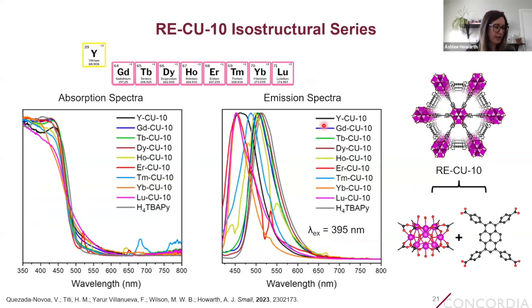We also need to look at the photophysical properties. So this is the diffuse reflectance UV-vis absorption spectra for all of these MOFs, where you can see that the absorption bands are primarily dominated by pyrene pi-to-pi star transitions, although we do see some f-f transitions from some of the lanthanoid ions in the MOF. And we can also look at the solid state emission spectra, where we see that, again, the emission is also dominated by pyrene, where in some cases we see pyrene monomer, and in other cases we see pyrene excimer emission.